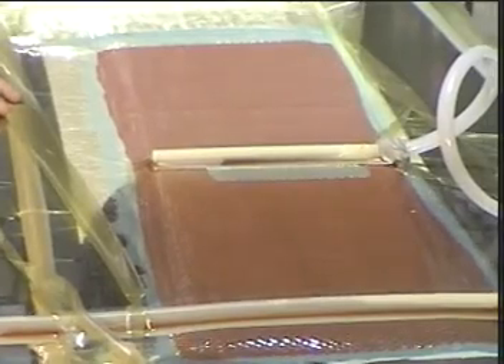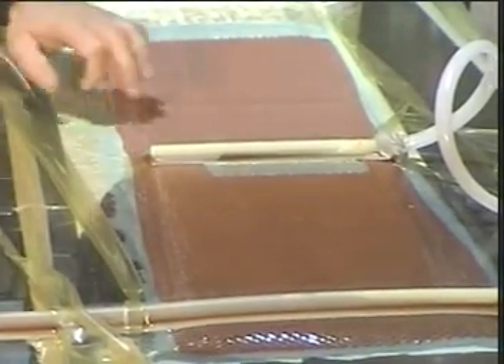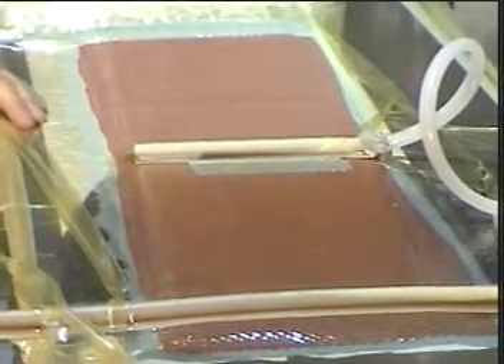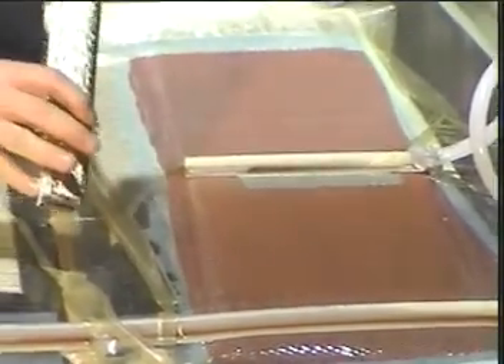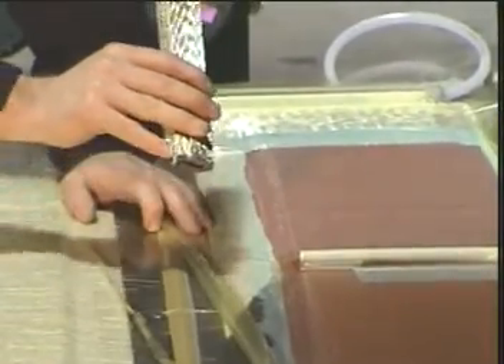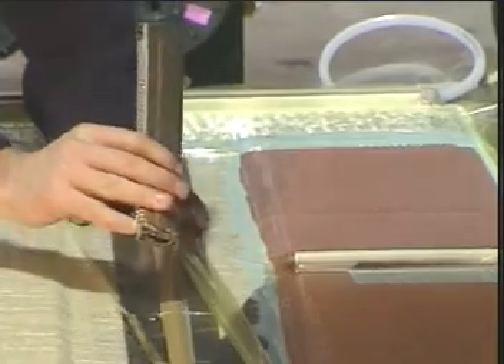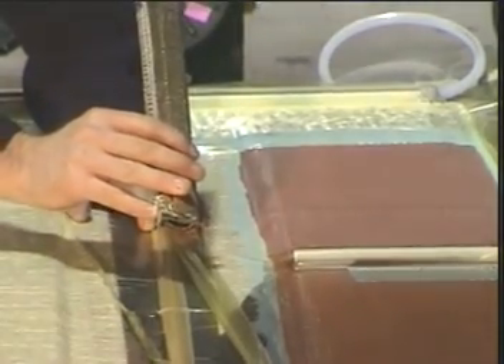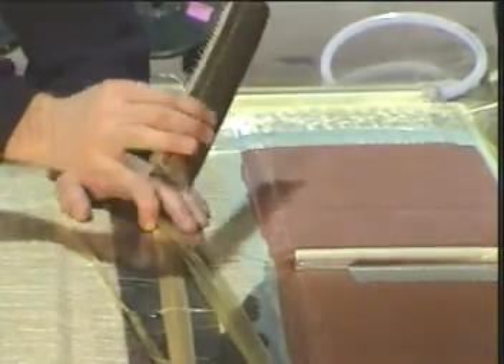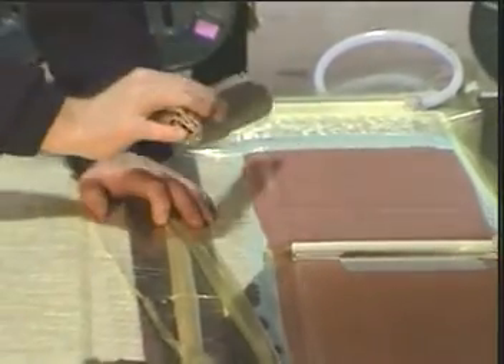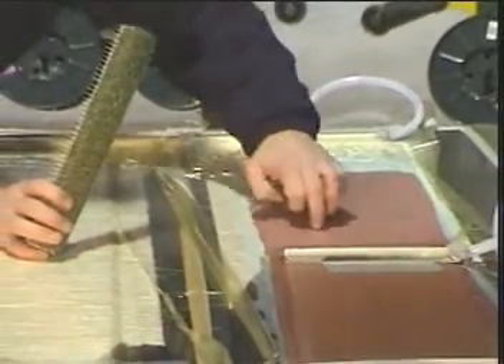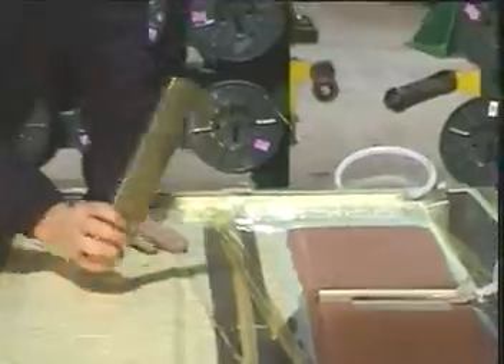Here in our scrimp panel, we have moved across the top of the panel in the distribution media, but we're starting to run out of steam, a little bit of steam. If you were to monitor the infusion flow, you'd actually see it moving very quickly over the top, but slowly through the thickness in this high-density panel. What that can lead to is at the end something called a waterfall effect, where it actually falls over the back of the panel, leaving a big dry spot on the inside.